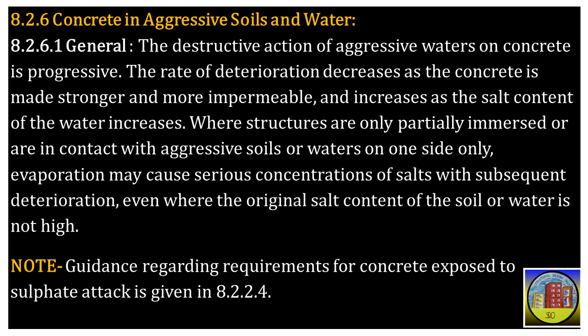8.2.6.1 General: the destructive action of aggressive waters on concrete is progressive. The rate of deterioration decreases as the concrete is made stronger and more impermeable, and increases as the salt content of the water increases. Where structures are only partially immersed or are in contact with aggressive soils or waters on one side only, evaporation may cause serious concentrations of salts with subsequent deterioration, even where the original salt content of the soil or water is not high. Note: guidance regarding requirements for concrete exposed to sulfate attack is given in 8.2.2.4.